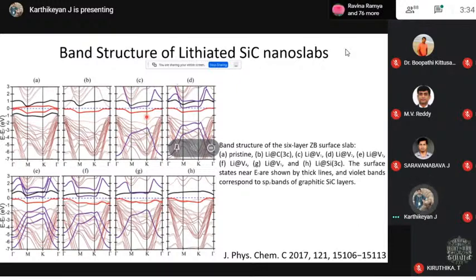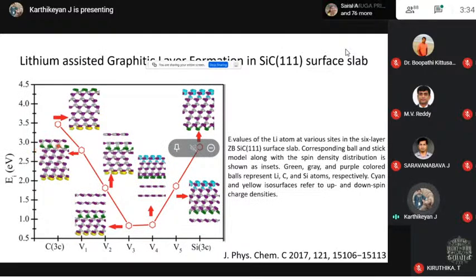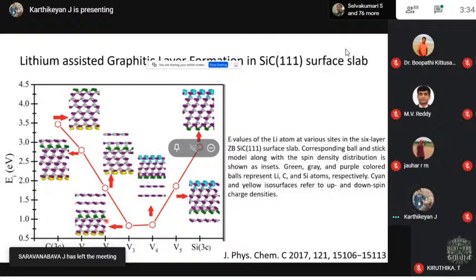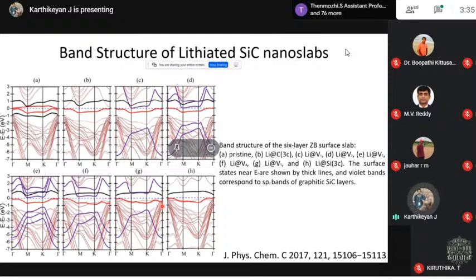But when you add a lithium just below the first layer, now you can see that there is a band which is shown in a purple color that gives a band of a single layer. You can see that when you add a lithium right below the first layer, it forms a graphitic layer here. When you add a second layer, it forms 2 graphitic layers. When you add it below the 3rd layer, it forms 3 graphitic layers. When it goes near to the other side of the surface, it forms a graphitic layer on the other side. So this lithiation increases the tendency of forming graphitic silicon carbide layers. That is our understanding from this lithiation, and we made it as a mechanism for these silicon carbide based anode materials.